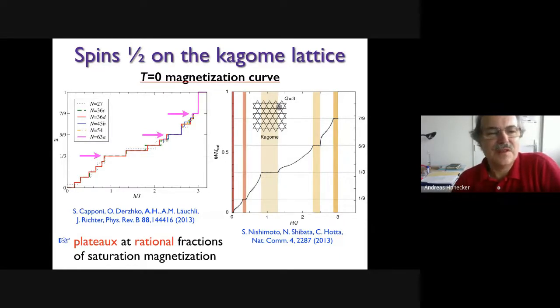So the point is that there's a tendency in such highly frustrated magnets to have rich physics. In particular, here you see plateaus in the magnetization curve on the left panel. It's something we did almost 10 years ago. The point is you have magnetization plateaus here at 1/3, 5/9, and 7/9 in the magnetization curve. The other steps are finite size effects, because these are small systems.